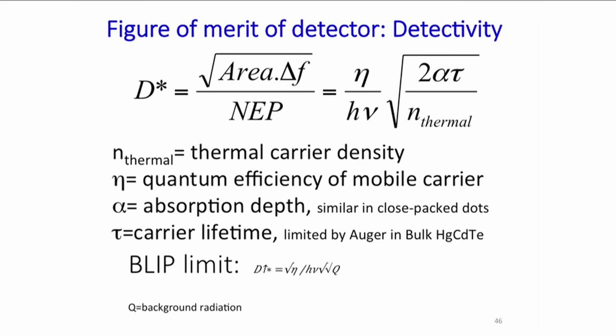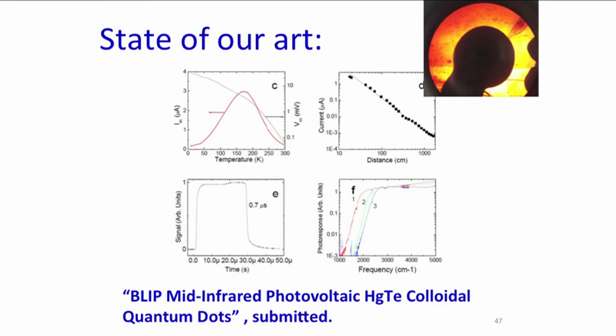Now, where we want to go is when this is limited not by the intrinsic noise of the material, but by the background. So this is some sort of a benchmark, that if the noise, the fluctuation of the number of photons coming onto the detector, is the limiting noise, this is the benchmark. And so we just recently got there with the mercury telluride quantum dots. So they were photovoltaic devices. And so what is shown here is a number of features about those materials. When you cool them down, the open circuit voltage increases in some sort of monotonic fashion. The short circuit current increases up to its peak value, but then it decreases again.